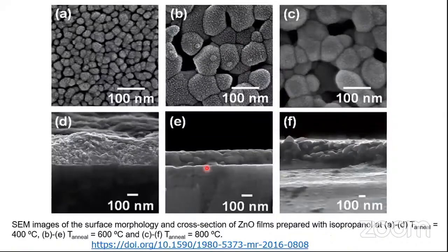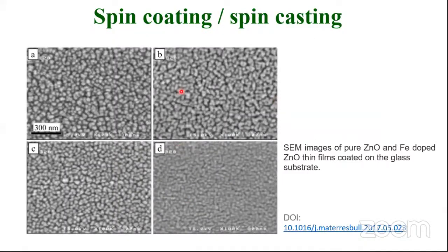So these are some other structures. These are images of nanoparticles formed over the substrate, and these are the images of the samples after annealing. You can see the surface structure, which is embedded with a large number of nanoparticles. This is another case, which is very fine. The scale bar is 30 nanometers, so I think these particles are 10, 15 nanometers. Only a few layers of nanoparticles are created over this substrate.